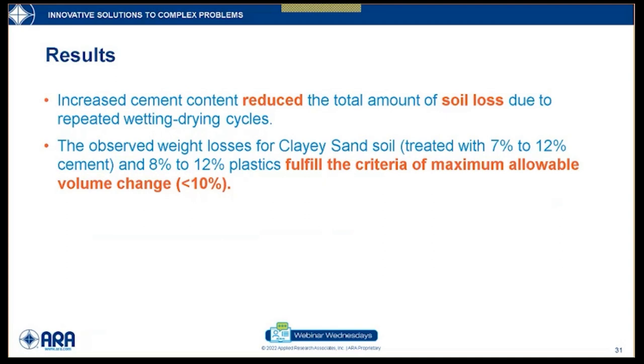The results of the durability cycle show that the increased cement content reduced the amount of soil loss due to the repeated durability cycles. And the soil samples treated with higher doses of cement and plastics of regrind flakes fulfill the criteria of maximum allowable volumetric change, that is less than 10%.